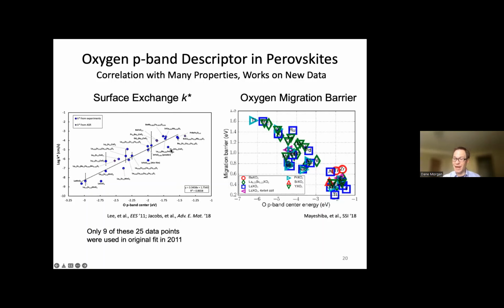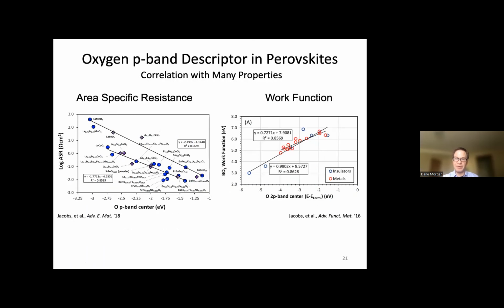We've also found that a lot of other things seem to correlate with this p-band descriptor. For example, we calculated about 40 migration barriers for oxygen to diffuse in a bunch of different perovskite systems, and we plotted them against this oxygen p-band center energy, and in fact, again, found very good correlation. As you increase the p-band, the barriers to move oxygen decreased in the system. It's not perfect. It's not like it perfectly controls the barrier to move oxygen, but there's clearly a very strong trend there. And we've seen this in other properties.